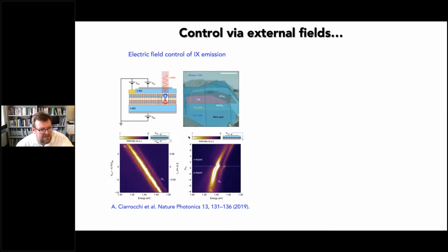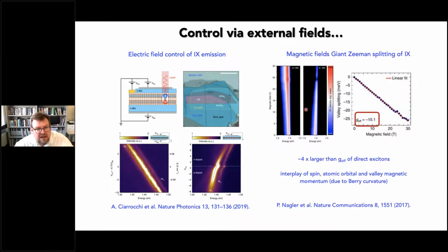So this shows the interlayer excitons are very interesting. This shows that they have a dipole moment. If you put electric fields around them and you apply electric fields, just like a static dipole in an electric field, it should shift in a linear way. And they do indeed, as the voltage is changed, show very nice linear Stark shifts. You see very large Stark shifts, much, much larger than the line width. Moreover, there's a lot of beautiful, extremely interesting magneto-optical effects, which I don't have time to go into, but I could give a whole other hour-long talk about this kind of stuff.